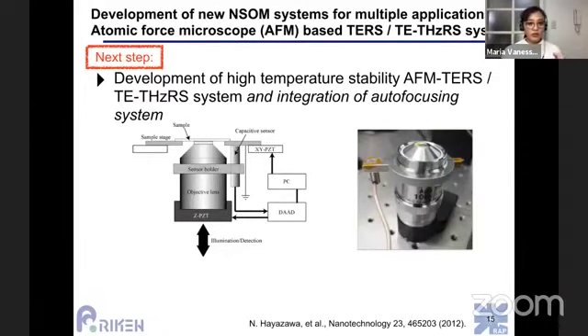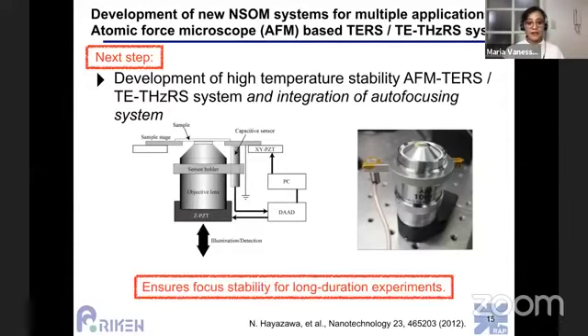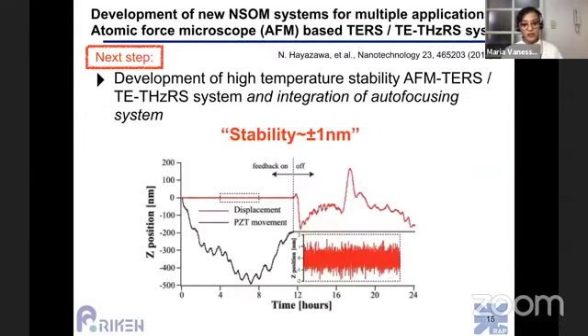And another factor which we want to consider so that we can also shift to what we call long measurement times is that we want to ensure that the laser focus on the sample is always at focus. To do this, we have implemented a system wherein we use a capacitive sensor, which helps maintain the focus spot position of our objective lens. And the stability of this system is plus minus 1 nanometer.